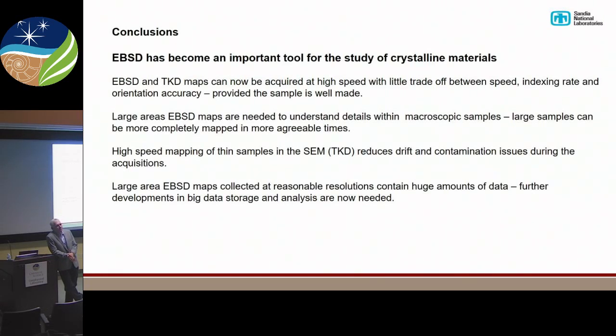Oh, let's see. We have tried to look at things that are either extremely fine-grained, nanometer sized, and we run into some problems there with the resolution. Again, the sample has to be extremely thin at that point, so that tends to be a problem. If we start to get into things that aren't crystalline, you might be able to do nearest neighbor sort of things, although it's difficult in that area, hasn't been studied a lot.